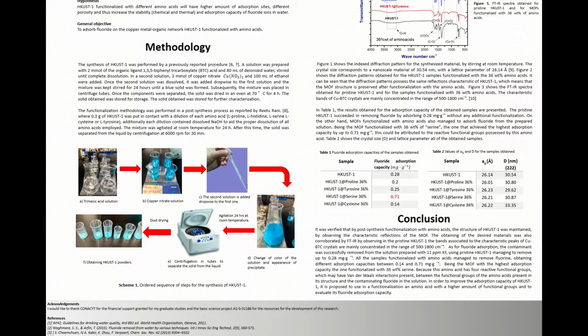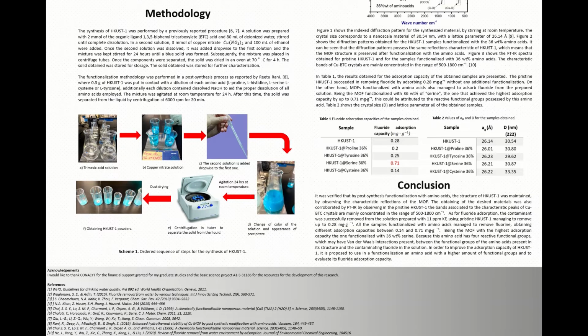Regarding the methodology followed for this work, the synthesis of HKUST-1 was performed by a previously reported procedure. A solution was prepared with 2 millimole of the organic ligand 1,3,5-benzenetricarboxylic acid and 80 milliliters of deionized water, stirred until complete dissolution. In a second solution, 3 millimole of copper nitrate and 100 milliliters of ethanol were added. Once the second solution was dissolved, it was added dropwise to the first solution and the mixture was kept stirred for 24 hours until a blue solid was formed.